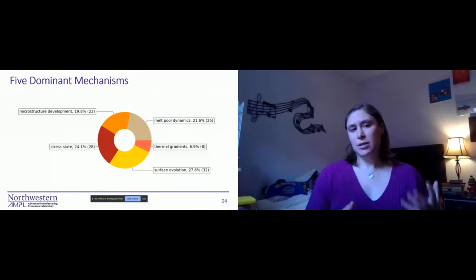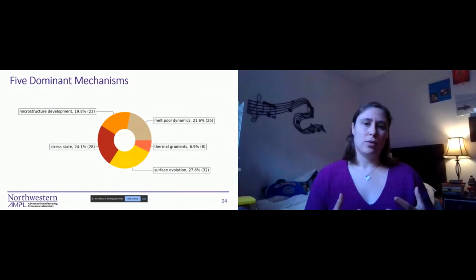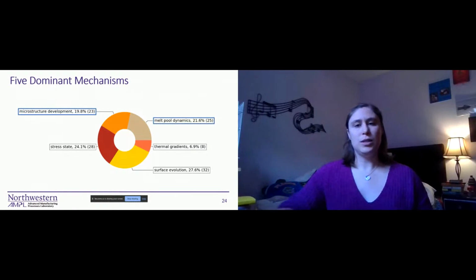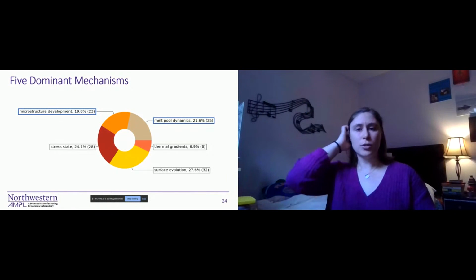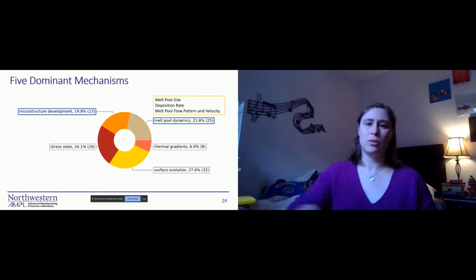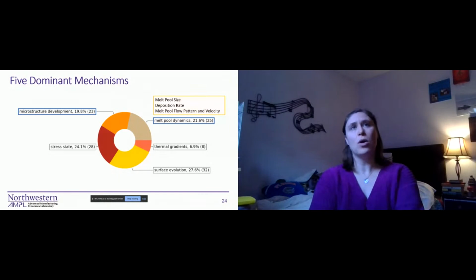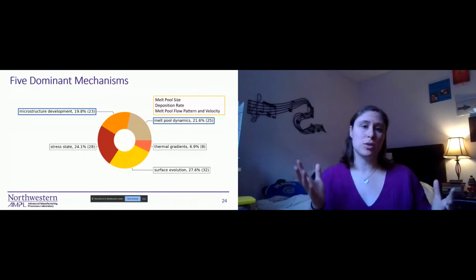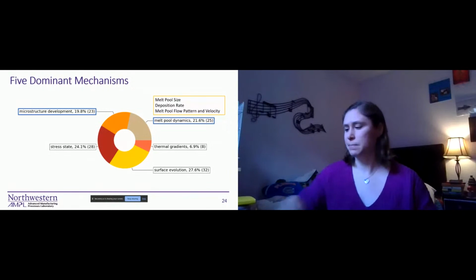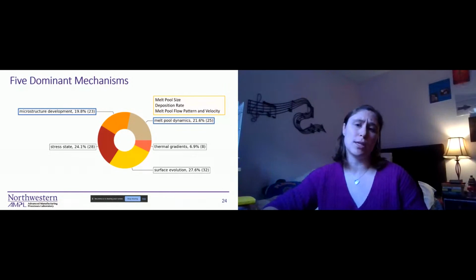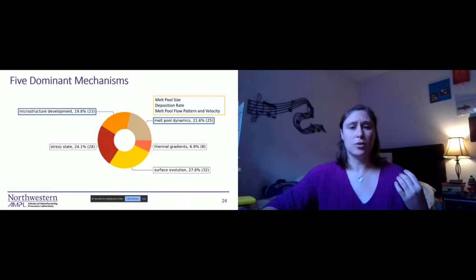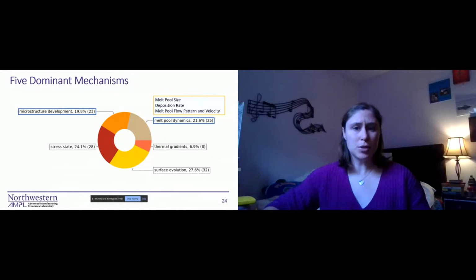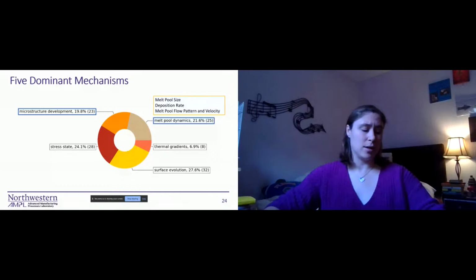So revisiting the 5 dominant mechanisms, I'm going to go into detail on 2 of them. The first is going to be melt pool dynamics, where we're going to look at how specific processes can fit into this framework and how this framework can be utilized. So again, melt pool dynamics specifically looks at how to control the melt pool size, the deposition rate, or the melt pool flow pattern and velocity.